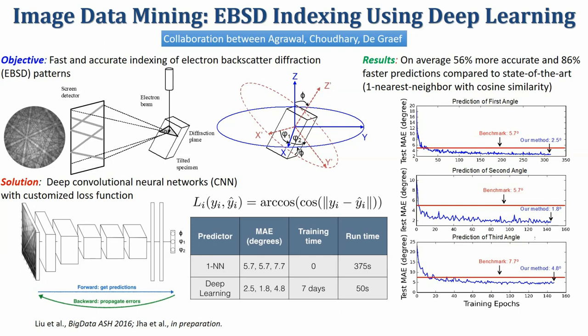In the image space, we have looked at electron backscatter diffraction images. So I don't have to give the introduction of what EBSD is. That indexing problem, of course, is in collaboration with Marc De Graef at CMU. So the indexing problem is, given an image, we want to find which crystal orientation it came from. In the Euler space, you can represent it by 3 angles, phi 1, phi, and phi 2. So we developed a deep convolutional neural network with a customized loss function, which can do exactly that: take this image and give these 3 angles.